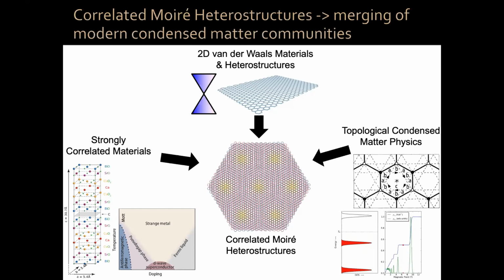Mm-hmm. Very good, very interesting. So first of all, graphene is not truly electron-hole symmetric, okay? It's only when you look at very low energies in graphene itself that it looks particle-hole symmetric. Once you include next neighbor hopping terms, etc., the electronic structure of graphene is asymmetric. All that asymmetry at high energies falls down to lower energies when you make a Moiré superlattice, okay? So already at the single particle level, the electronic structure is not symmetric for electrons and holes in magic angle graphene. Separate from that, around the correlated insulator states, the electronic structure is already non-symmetric, okay?